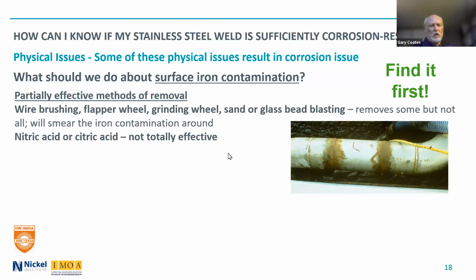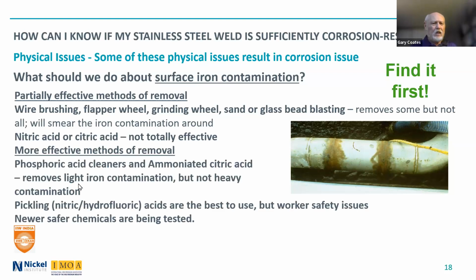Now, some people will use wire brushing or a flapper wheel or a grinding wheel to remove it. It's partially effective. It certainly removes the rust part of it, but does not necessarily remove the iron contamination that might not have started to rust yet. Nitric acid, citric acid, they're used for passivation. They're not totally effective. They might, again, remove some of the iron contamination, but we have done it ourselves on some pieces of equipment that have heavy iron contamination, and they are not effective that way. So the more effective ways, there are some phosphoric acid cleaners that are pretty good. They might need repeated use. Ammoniated citric acid, again, is one that removes light iron contamination better than pure citric acid, but doesn't remove the heavy iron contamination.